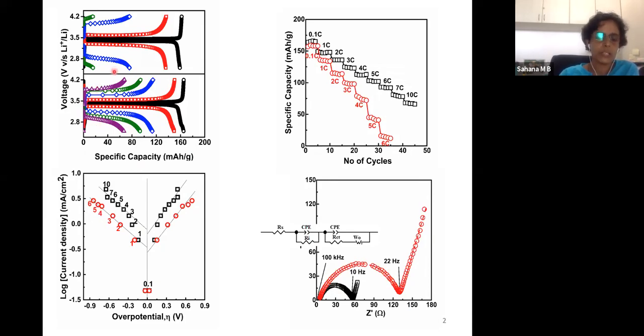Take one common color, let's say, for example, the green one. The green on the top is done through sequential mixing, where we add carbon first and then LiFePO4. We can see the loss in the energy or specific capacity is very high, because charging happens at a high voltage and discharging happens at a very low voltage. Compared to the similar line here, the green one in the down, where we first pre-mixed carbon black and LiFePO4, the loss in the energy is low.